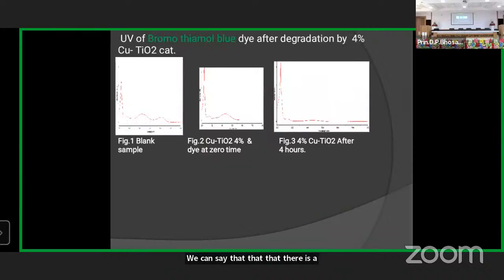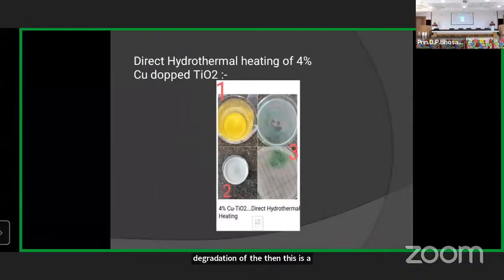After that we checked whether it is real or not. For that we did the UV. The second one is with the 4% catalyst, and the third one is with the 4% catalyst after 4 hours. At zero time there is one small peak, and after 4 hours we got a straight line, so we can conclude that there is a degradation of the dye. Then this is a picture at the time of preparation. In this way, the first stage of copper doping is done.